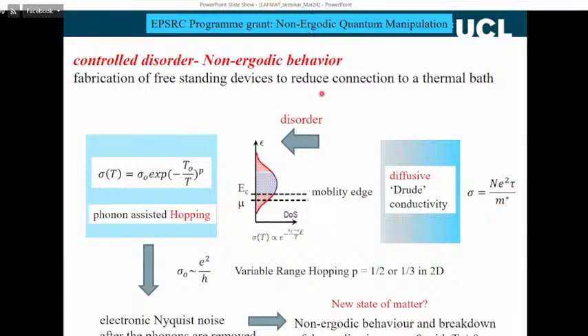When we introduce disorder into the system, we can do that in many ways. We can ion beam damage them. We can put doping in there. That creates this disorder, and we get something called a mobility edge. This diagram in the middle here shows the density of states in the conduction band as a function of energy. In the middle of the band we have conducting states, we have a mobility edge.